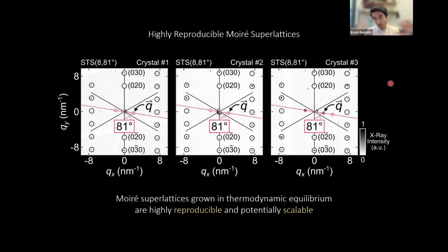In addition, because we're growing superlattices in thermodynamic equilibrium, when you do diffraction on any crystal within a batch with the same growth profile, with the same catalyst, with the same precursors, you find identical diffraction patterns. Particularly, these Moiré superlattices are highly reproducible. And so if you're interested in using Moiré materials for next generation electronics, I implore you to use chemical pathways that emulate some of the chemistry that we've discovered and discussed in our paper.